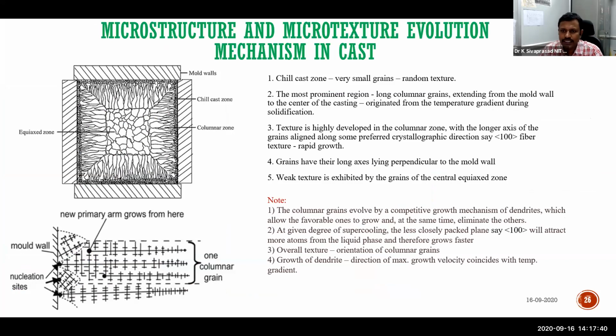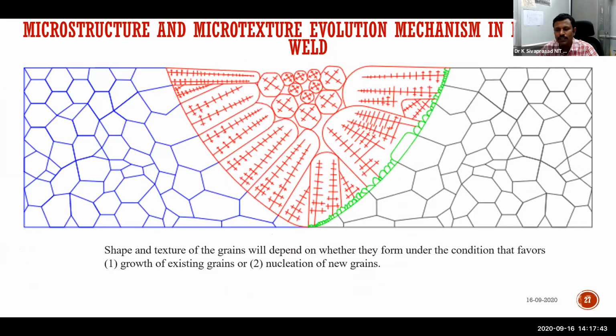And this is a schematic associated with what we got on the dissimilar side. On the steel side, we got type 2 boundaries which are similar to this. Thereby, the coarser dendrites are formed. On the left side, it is an epitaxially grown structure. So, matching grain size and matching dendrite size were observed in the epitaxially grown structures. So, this clearly evidences why this differentiation is observed. But to our surprise, in fact, this has favored us. Otherwise, if it had been a similar kind of structure, the gradual property variation from this to this could not have happened.